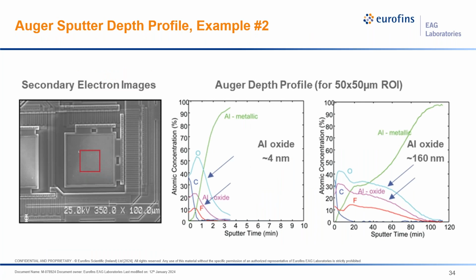A lot of different applications we use Auger for. In this case, just bond pad issues with bonding. In these two examples here, on the left depth profile, we have a standard typical depth profile for a well-performing bonding sample for an aluminum bond pad. Typically, we find an aluminum oxide layer 4 to 5 nanometers thick with the aluminum oxide present and also some fluoride in there as well. And on the right side, we have a non-bonding problematic bond pad here where the oxide layer is about 160 nanometers. So there's some corrosion going on here.